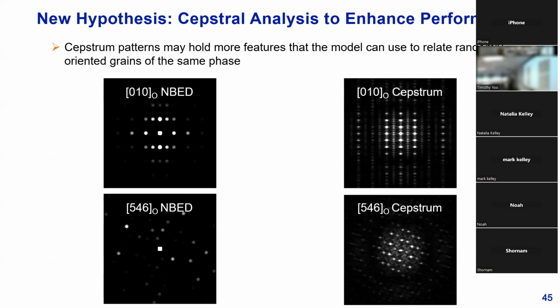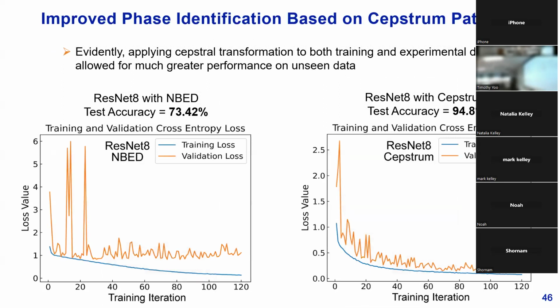And we also see that now the 546 Cepstrum also has some symmetry features. So now my thinking here was that maybe the model can then learn to identify phases, not necessarily by spot arrangements or the spot spacings, but maybe rather by certain symmetry features that existed amongst all the diffraction patterns in this case. And so just getting right into it, that's exactly what we see.